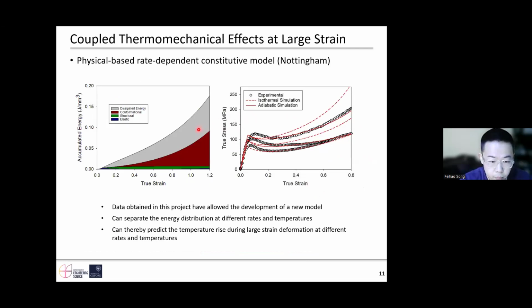Here is the model. This model can separate the mechanical work into dissipated, conformational, structural, and elastic energy. And this model can simulate the quasi-static, medium rate, and high rate tests well. The reason for less softening is that, in the high rate test, the side chain or secondary motion of the polymer will be fixed, so a greater percentage of conformational energy is needed to fix that chain. So less heat energy will be generated, so less thermal softening.